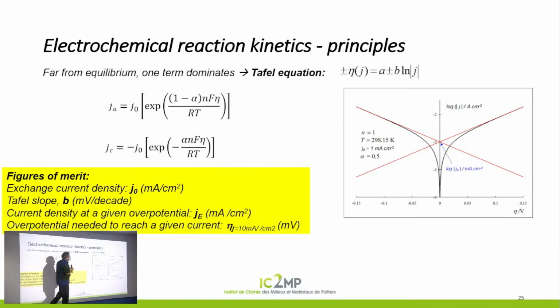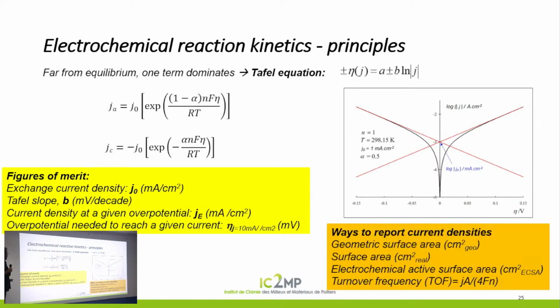So you see that the intercept here is the point that corresponds to the exchange current density for a reaction. So we have several figures of merit. Here is the exchange current density, the Tafel slope, etc. The most common way to report the current density is with the geometric surface, but that is not really true. If you take into account the real surface, then you have to report the current versus the real surface. But that is not true for electrocatalysis.